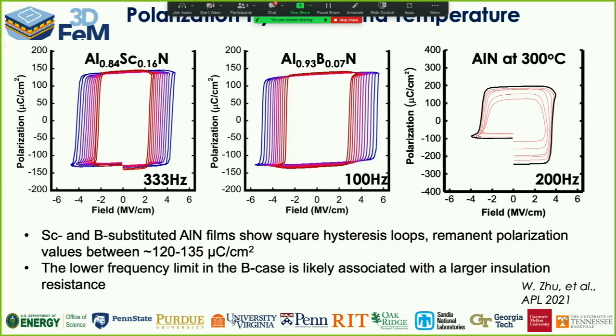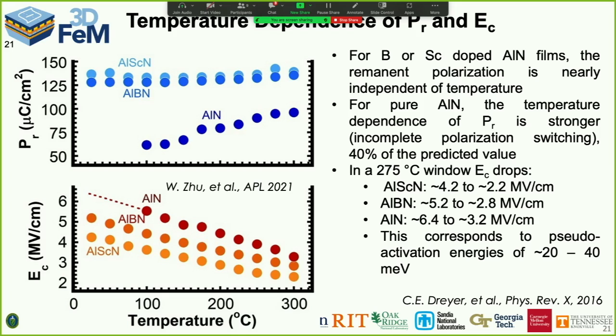Very cool. And so this shows data on aluminum scandium nitride, aluminum boron nitride, and aluminum nitride measured as a function of temperature. You can see that the hotter it is, the lower the coercive fields are, but the loops stay very, very beautifully shaped. And look at the magnitudes of the polarizations. 125 microcoulombs per centimeter squared. That is polarization to burn. For an electrical engineer, that says I can scale my material laterally because I will have enough electrons to measure switching very small, absolute sized capacitors.